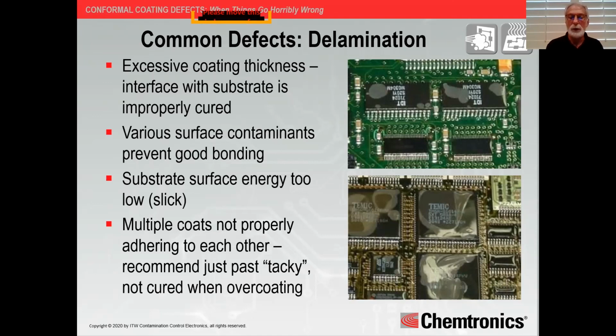Okay? And we always recommend on the previous coat, allow it to become tacky. Don't overcoat it while it's still essentially wet. You're running the risk of those coatings not adhering to each other. Actually, that's called cohesion.